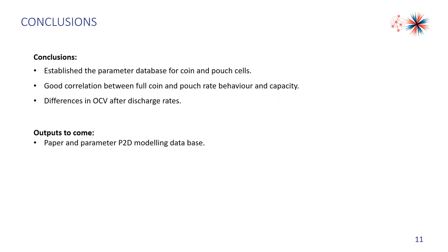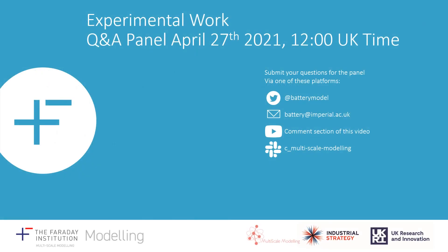So here are the conclusions. By performing the validation, GITT and EIS tests, and the electrode calibration, we obtained 35 parameters and established the parameter database for coin and pouch cells. The results show there is a good correlation between full coin and pouch cells in behavior and capacity. However, there is a little difference in OCV after discharge at high C rates, which may be due to the mass loading deviation on the electrode. We have finished the paper draft and hope we can provide parameters and database for P2D modeling. If you have any suggestions or questions on this research, please let us know on this channel.